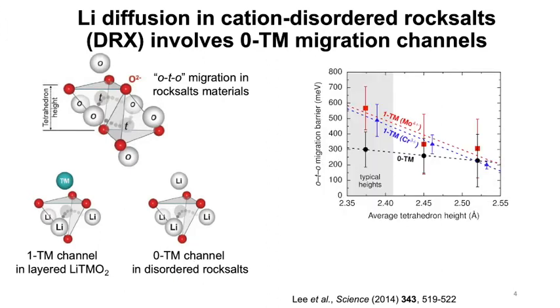NEB calculation of the lithium migration barrier can help us understand why there is such a difference. This figure shows the o-t-o lithium migration barrier versus the average tetrahedral height, which represents the size of the intermediate tetrahedral site along the lithium migration path. As we can see, when there is a large tetrahedral height, which is the case for the layered rocksalt structure, the lithium migration barrier along the 0TM pathway versus along the 1TM pathway is not that different. However, in DRX material, the average tetrahedral height is reduced because of cation mixing, which is represented by the shaded region in the figure.